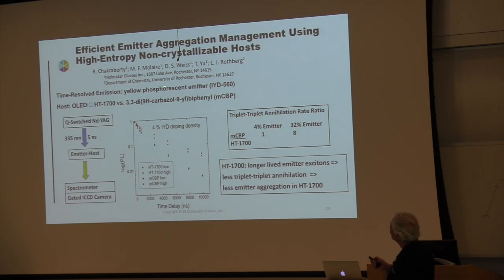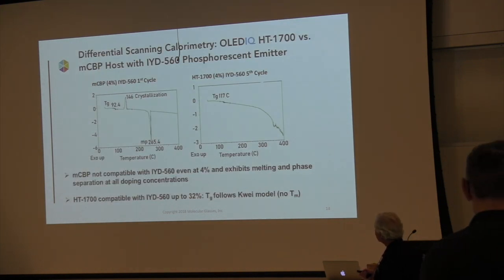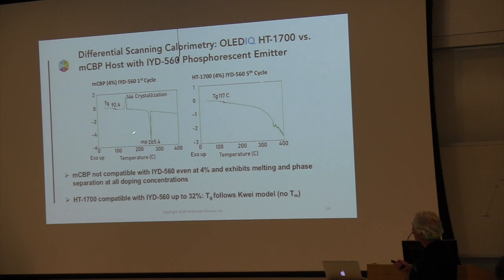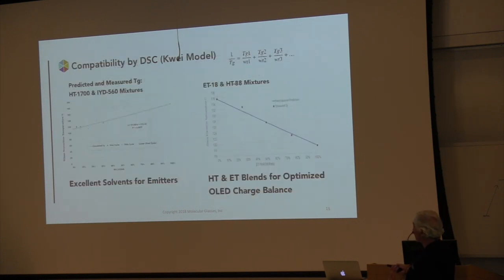Now I've only got 2 minutes, so this is a poster we have out there. One of our hypotheses was that our materials are great solvents and never crystallize, and we've done some collaborations with the Rothberg group at the University of Rochester, and we find that in our materials, a particular emitter has much longer lifetime. And then we did differential scanning calorimetry and found out, in fact, that that particular emitter, when it was put in a standard MCBP, tended to crystallize, whereas when we put it in our material, it didn't crystallize. So our material is definitely a better solvent, and in fact, our material followed the Kwei model.